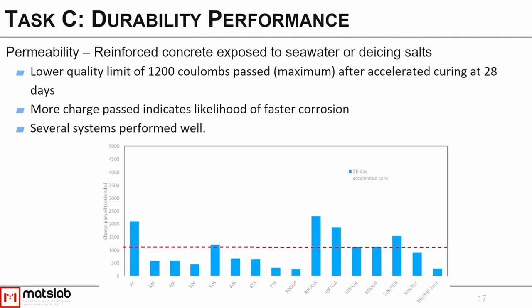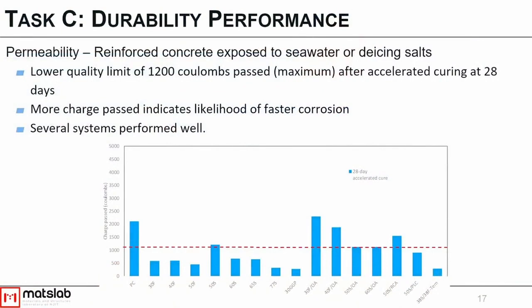We also looked at durability performance. So this is rapid chloride penetration testing. If you're familiar with that test, you pass a charge through a chunk of concrete, and based off of the amount of charge passed, you can have a rough idea of how resistant it is to chlorides moving through it that may cause corrosion. So we have a lower quality limit, meaning that in order for it to be acceptable, it couldn't pass more than 1,200 coulombs of charge.